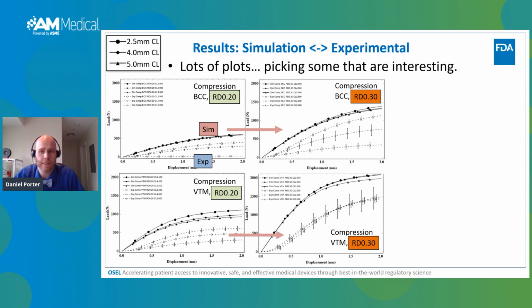The Voronoi is a stochastic structure and eventually leads to blind crevices, which makes powder removal and verification of residual powder difficult. Additional powder actually could reinforce the lattice sample and affect the compression modality giving a stiffer mechanical response. This information is interesting because it may need to be considered if we ever design a test standard. So you have to consider how feasible it is to remove powder from a sample that you're going to create and test.